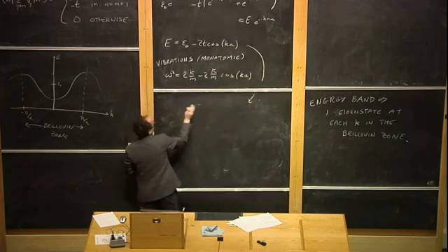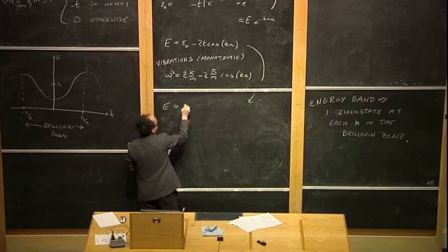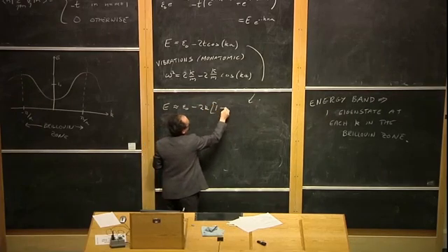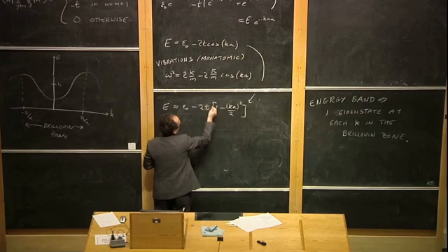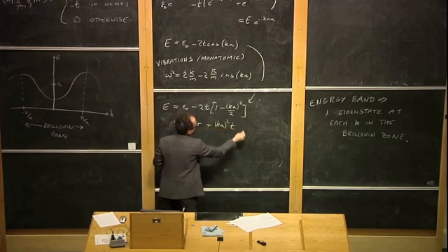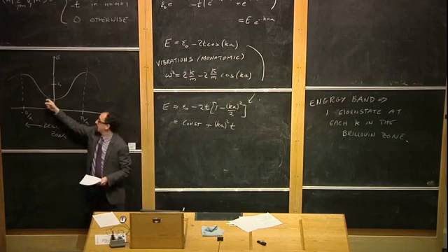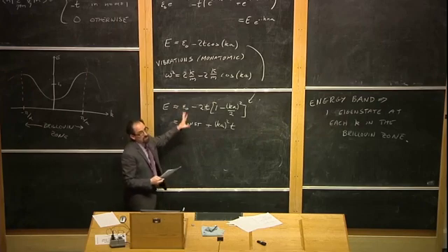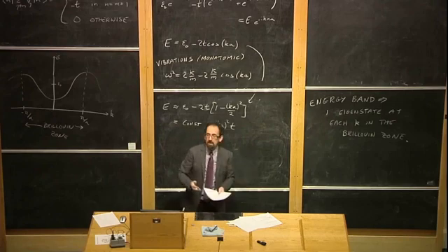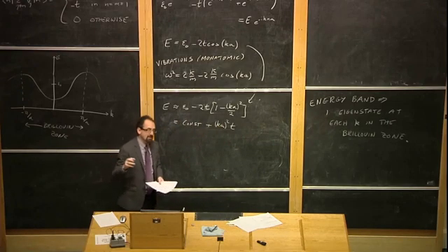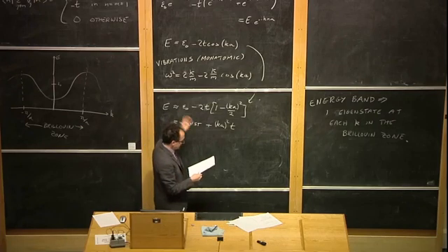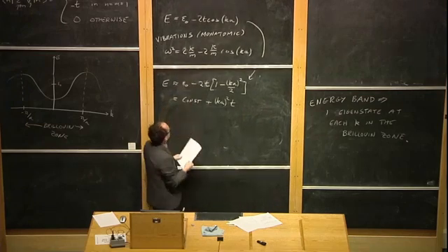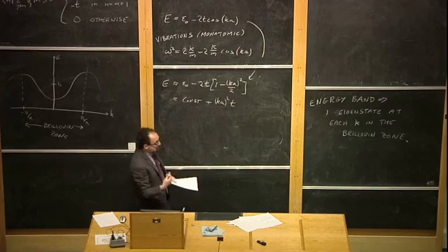In this picture, in the case of electrons, if you expand near zero wave vector, it's E naught minus 2t, and then we substitute in for small wave vector Ka squared over 2, and we get a constant, which I'm not interested in, plus Ka squared times t. It's quadratic at low energy, as you would expect from a cosine. And that's why we do not use the word acoustic for these low energy modes. Acoustic modes, by definition, sound modes, have linear dispersion: the frequency should be proportional to wave vector. That's the definition of sound. So here it's quadratic, so we don't call it acoustic, and we don't call it optical either if there's higher energy branches. But this picture of the energy being quadratic in wave vector should be fairly familiar to you from